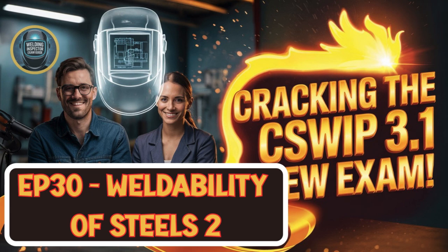We're talking tiny amounts of elements like aluminum, niobium, vanadium. These act as grain refiners. Grain refiners, what does that mean? Basically, they help create a much finer internal structure in the steel, smaller crystals or grains. And smaller grains generally mean higher strength and better toughness. It's kind of amazing, really. Just a tiny pinch of these elements and boom, you get a much tougher, stronger steel. Shows you the precision involved. A typical example you might see in pipelines or heavy equipment could be something like API 5L grade X65, or even higher grades like X70 or X80.